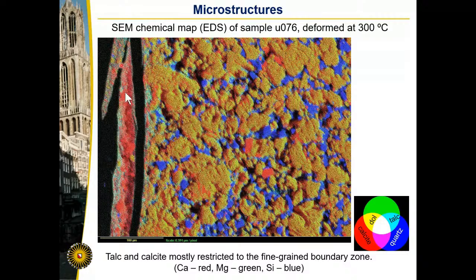But very importantly, in this boundary shear, we see almost no more dolomite, and we see lots of cyan colored grains and calcite grains as well. So this suggests that we do have talc that's being formed, but it's only forming on this boundary shear.